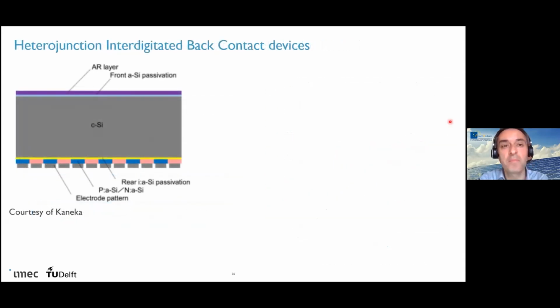This is actually a so-called heterojunction interdigitated back contact device—the current world record device in crystalline silicon. It's again a heterojunction device, meaning we use amorphous silicon layers to passivate the wafer, typically an N-type wafer, but now all the metal contacts are at the rear of the device. So at the front of the device, we have no metal contacts anymore, and therefore no shadowing losses.